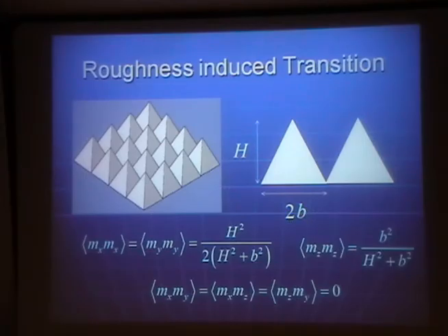And we can calculate the total free energy by simply assuming uniform liquid crystal alignment. What happens here is that the energy is dependent on capital H and B. If H is too high, then instead of the orientation being parallel to the surface, we get homeotropic alignment, where the liquid crystal is oriented perpendicular to the surface.